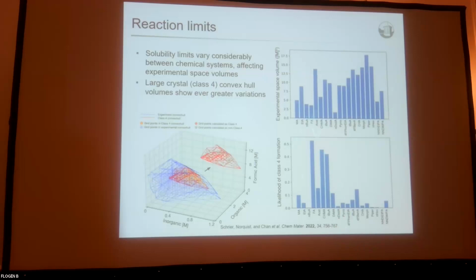There are some systems like formamidinium where the concentration windows are small, but the success of reaction is quite high, and then others, for example pyrazine, where the experiment convex hull is quite big, but there is very little success. Machine learning work on these data within a given system worked pretty well. We could do interpolation, and the model that we built could predict the outcome of the experiments quite well. But extrapolation between systems was much more of a challenge, and that was certainly much more difficult. But we wanted to expand this to see if we could add additional synthetic workflows.